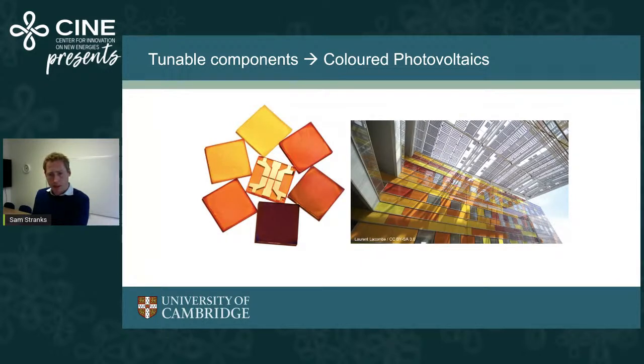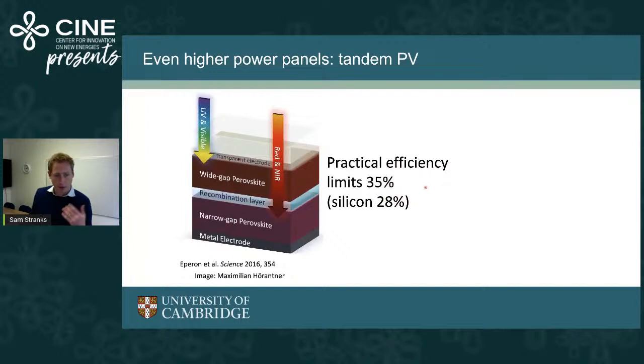But really where I see the most exciting opportunity for changing this band gap is actually using them in what's called tandem photovoltaics. So here, this is layering two subcells together into a tandem stack where the top cell harvests the blue wavelengths and then the bottom cell harvests the red wavelengths. And so in doing this, one can get around the traditional limits of just a single junction, which is typically an efficiency of about 30%. And theoretically, these efficiencies can go up to about 50%.